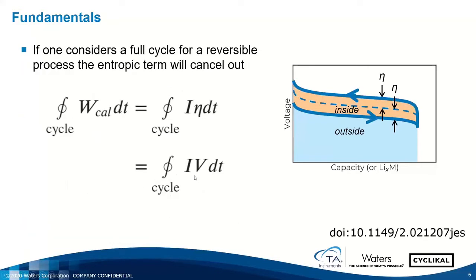So one challenge when we look at this equation is that the equilibrium potential is not necessarily known. So it may require some sort of more detailed experiments to get it, but we can sort of get around the fact that we don't necessarily know the equilibrium potential by looking at this equation over a cycle. And if we look at this equation over a cycle, what's really nice is that the entropy term cancels out, because the entropy on discharge will be the negative of the entropy on charge, right? So we have a sign change depending on direction. And if we look over a cycle, that term cancels out, and we're left with the overpotential term.